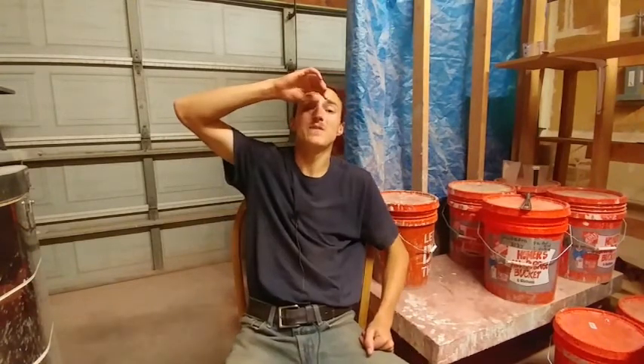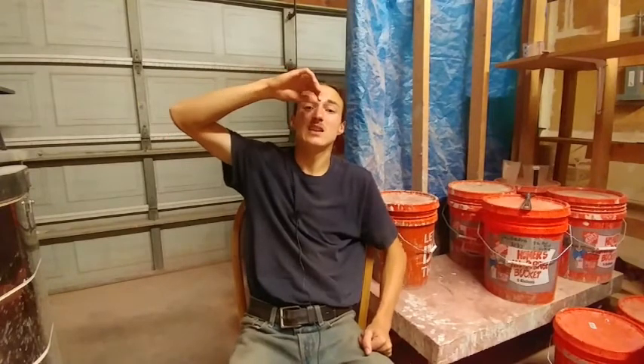You don't want something really high fire. You don't want to put your raw materials through a really high fire, because it can cause damage to it. It can alter it a bit. It can maybe burn it out. There have even been times I've taken raw materials and calcined them at cone 6, and the raw materials actually solidified into a rock, basically. So I don't calcine anything really high. I just go with cone 020. It works well for me.